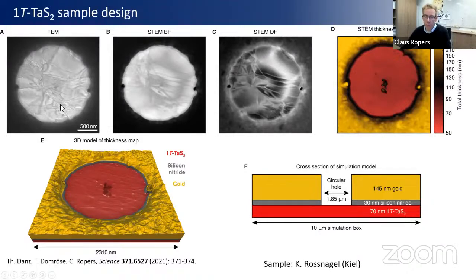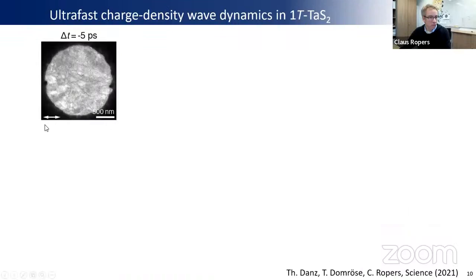Okay, so this is a scanning transmission electron microscope image. Transmission electron microscope images are just different ways of imaging the sample, either with a scanned focused beam or with a parallel beam. Essentially what you take from these images is that it's a relatively homogeneous sample. You have a little bit of a flaky nature of this 2D material, but it's in fact quite homogeneous. There's one point we need to consider with the optical excitation, as the pump pulse is impinging on the structure here. There's going to be some diffraction from the side edges of this mask, which is going to shape the optical excitation profile and the regions where the sample is going to be particularly prominently excited. Okay, so let's go to the time resolved experiment here.